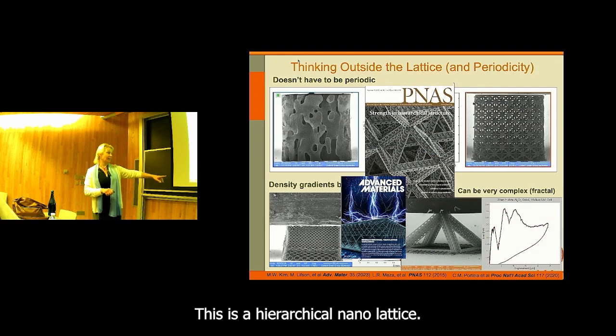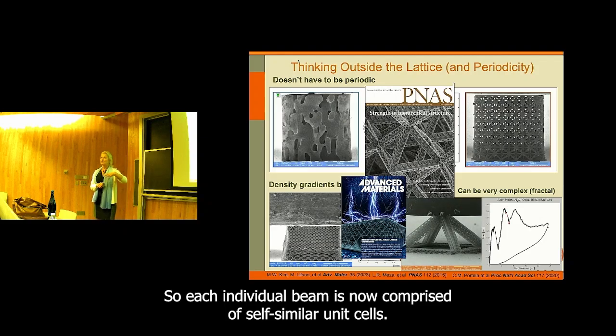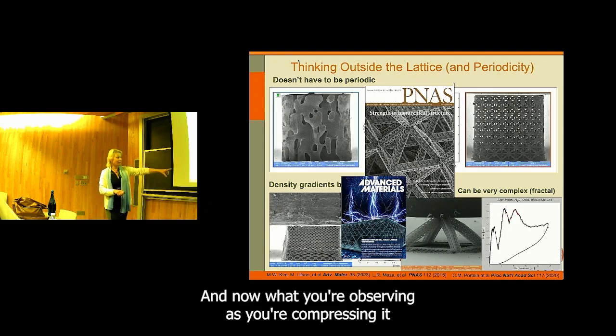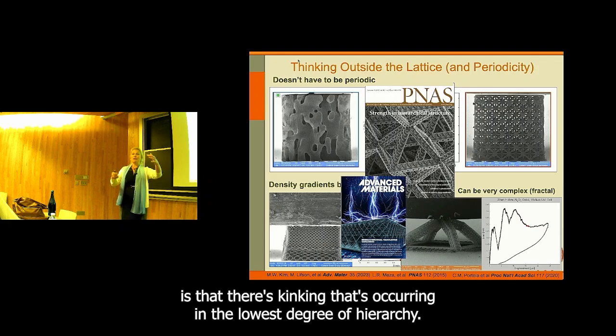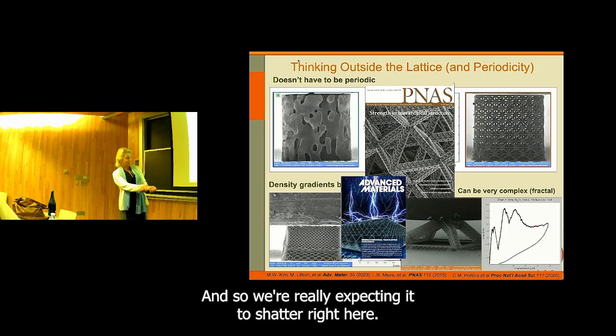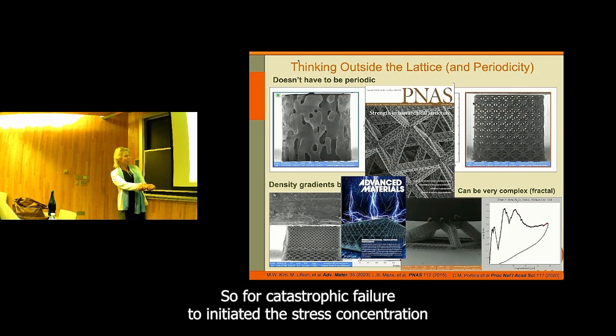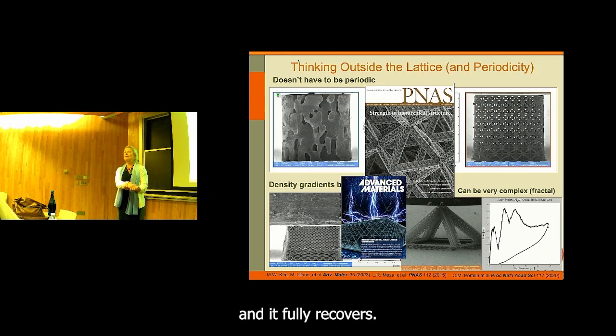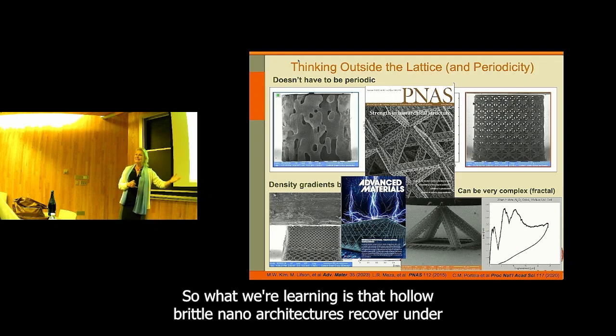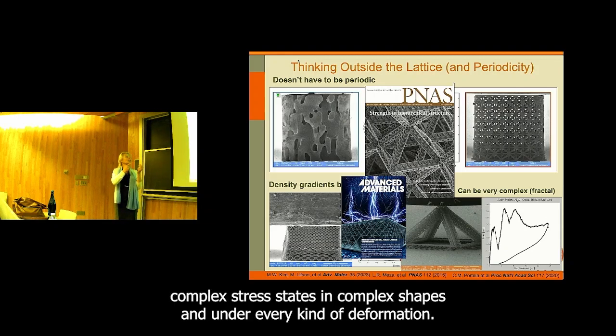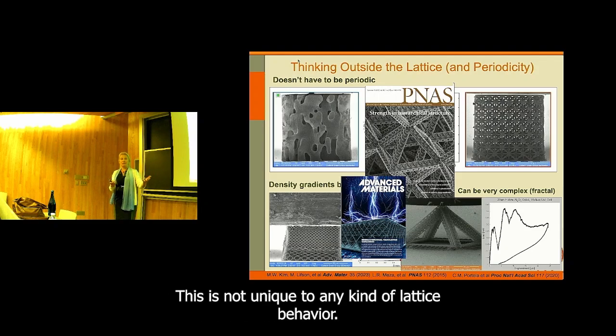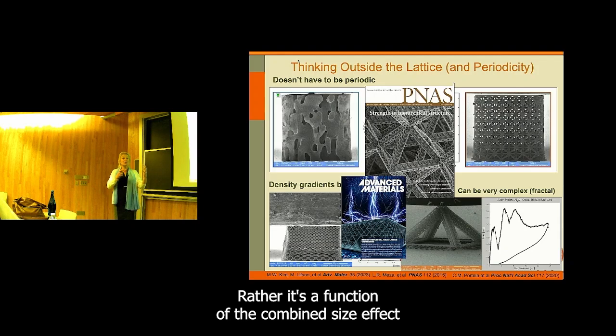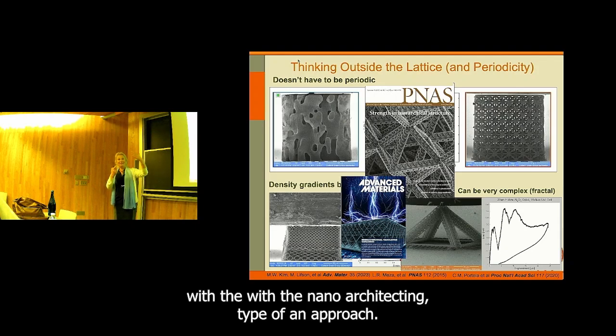This is a hierarchical nanolattice. So each individual beam is now comprised of self-similar unit cells. And now what you're observing as you're compressing it is that there's kinking occurring in the lowest degree of hierarchy. And so we're really expecting it to shatter right here, for catastrophic failure to initiate at this stress concentration, and it fully recovers. So what we're learning is that hollow, brittle nanoarchitectures recover under complex stress states, in complex shapes, and under every kind of deformation. So this is not unique to periodicity. This is not unique to any kind of lattice behavior. Rather, it's a function of the combined size effect with the nano-architecting approach.